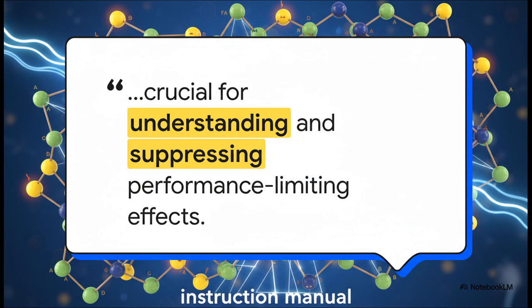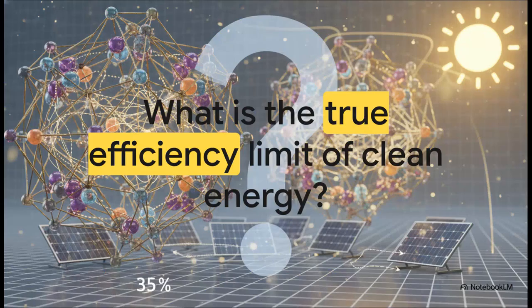Which brings us right to the core thesis of this entire explainer, pulled straight from the research. We know that a mechanistic description of these processes is crucial for understanding and suppressing performance-limiting effects. Simply put, we cannot fix what we don't understand. By using the Stark effect to prove exactly how light, heat, and dipole strength dictate ion movement, we finally have the instruction manual. We know that to suppress these performance-limiting effects, we need to carefully engineer the chemical mixture of those A-site cations, balancing things like MA, FA, and cesium to create an anchor strong enough to withstand the thermal kick of blue light.